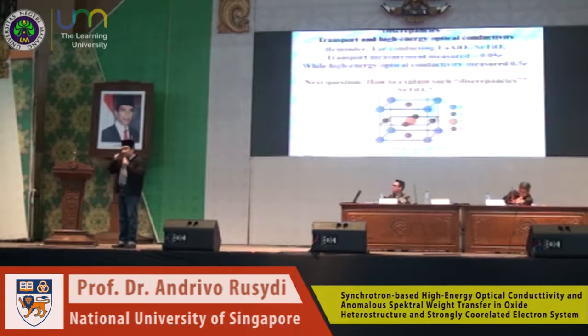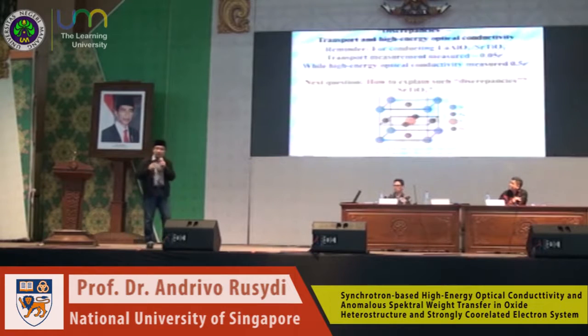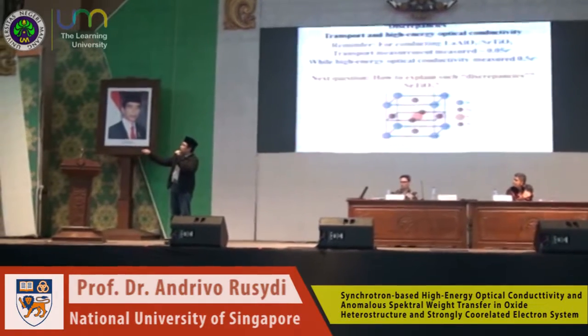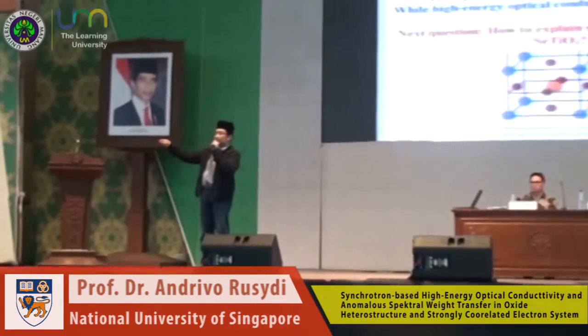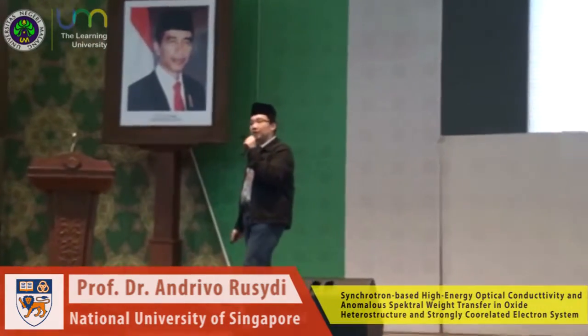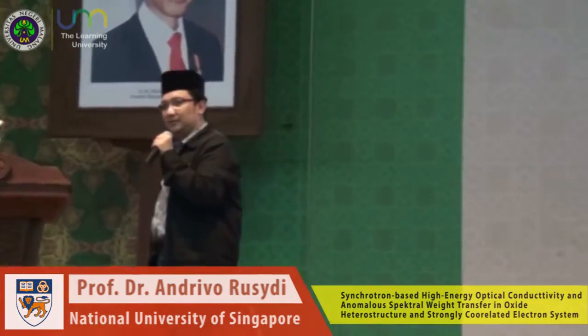But you always need to criticize your result. Yeah, it's very important that you criticize the result. So, what we found is that the high energy optical conductivity measures 0.5 electrons. That's the technique, the optical conductivity, the reflectance technique that we showed you. Transport, on the other hand, measures only 0.05 electrons. So there's a missing 0.45 electrons, right?